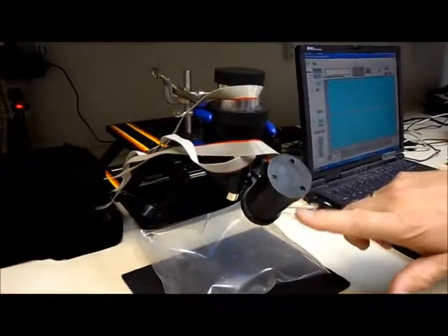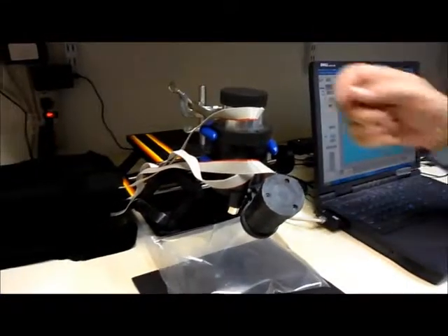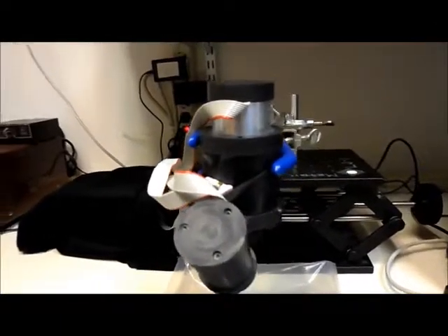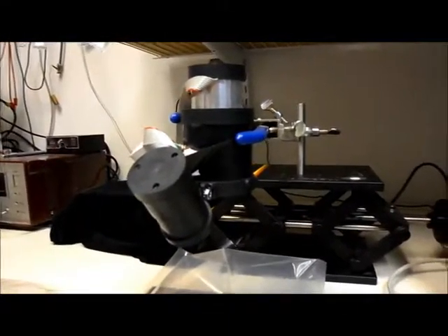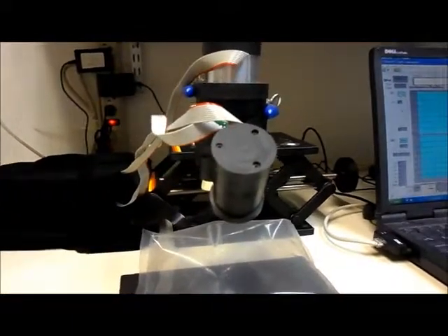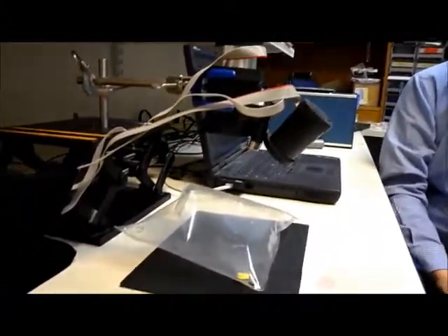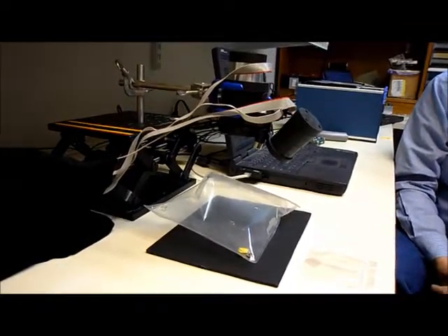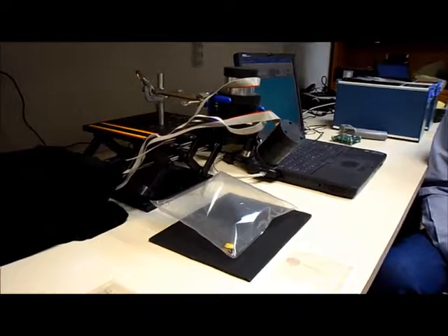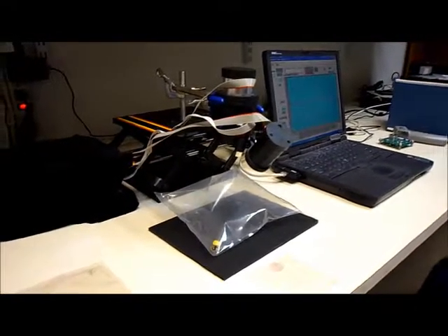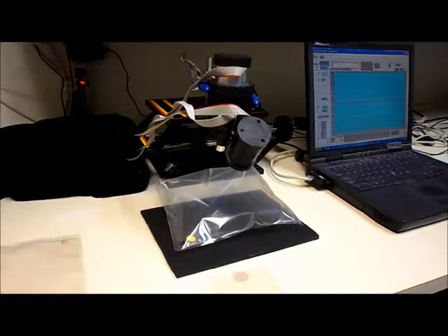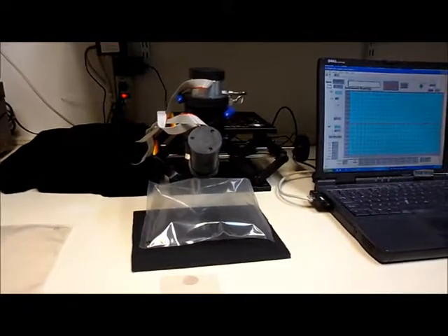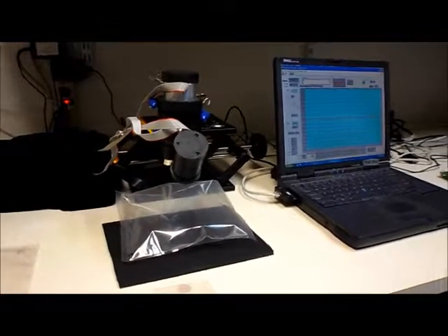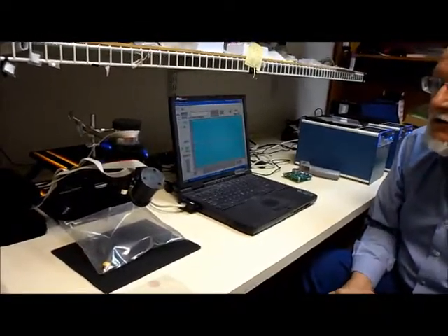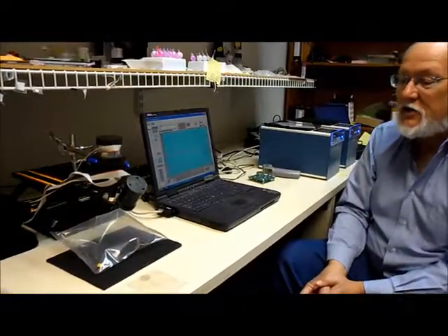This is a LED over here on this side of the instrument, and up in this portion at the top is a photodetector. We are projecting light onto the surface of the package. The red emission is being picked up by the optical head, and the lifetime of the signal is being calculated after the LED light is actually turned off. This LED is going off and on doing repetitive flash measurements of the surface of the package like 1,000 times a second. So we're getting an outgassing of the package and some oxygen going into the package.